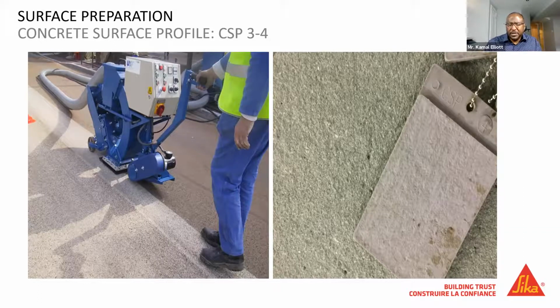bite into it essentially. This picture on the left shows a steel shot blast machine. It's an effective method in terms of getting that profile and removing laitance, also surface contamination. And on the right, you see an example of some surface profile pads, which are established by the International Concrete Repair Institute, giving us a sense of different textures. We like to get our deck membranes onto a surface that's in the CSP 3 to 4 range. We find that's the optimal surface texture. It's not too porous, and it's certainly coarse enough for us to bite into.